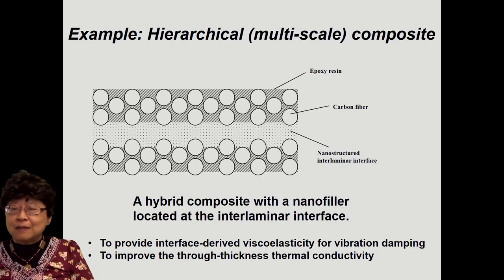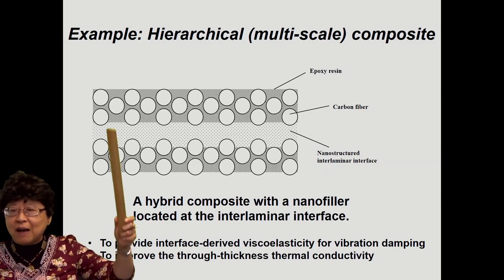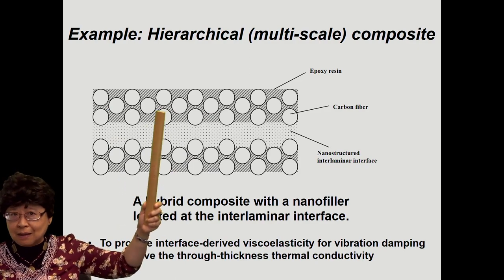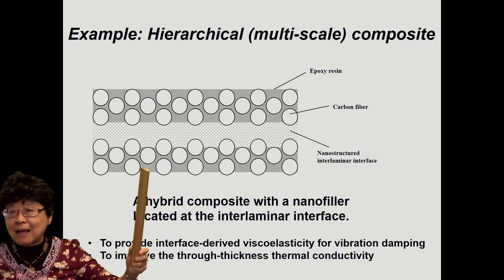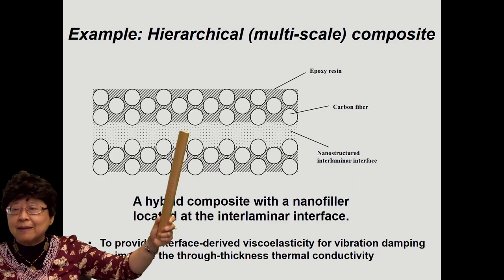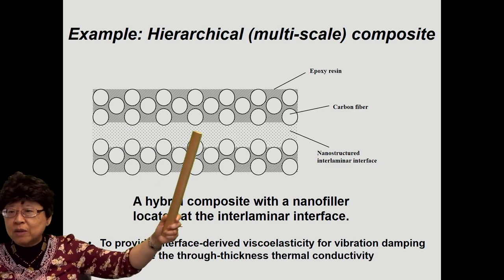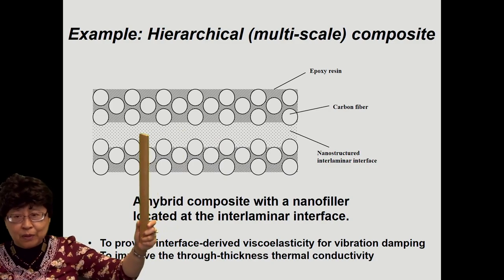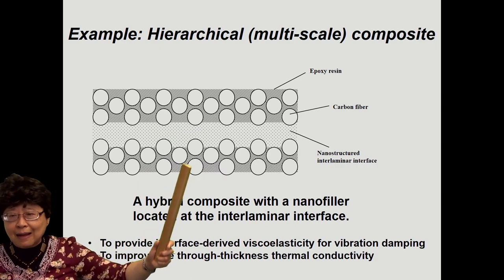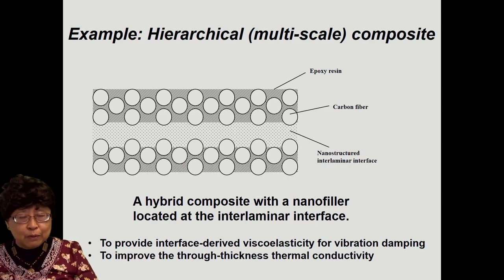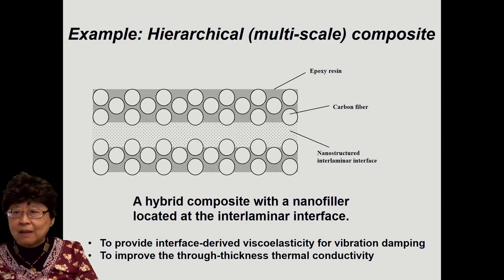Here's another example of interface-derived viscoelasticity that I also put forth. It involves carbon fibers. Carbon fibers are micrometer in scale, in diameter. But between the layers of the carbon fibers in a laminate, you have a region which is polymer-rich, and we can put some nanofillers, like nanofibers or nanoparticles, into this space. Because it's nano, you have a lot of interface area per unit volume. Therefore, the addition of this nanofiller in the space between the layers of the laminate would improve the viscoelastic character, thus improving the damping.